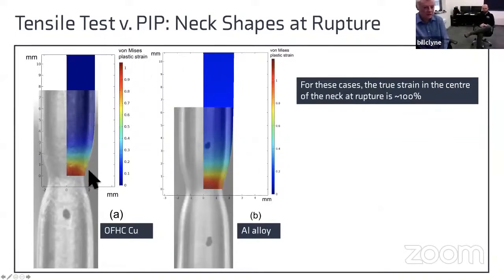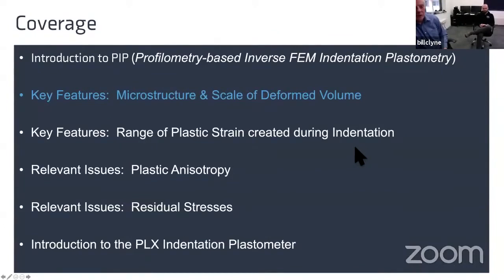These are the von Mises strains as a function of position here, obviously reaching a high value at the neck itself. This is just before rupture, and the level of true strain reached in the neck commonly reaches something like 100% or something like that. What else? Well, there's a number of important features of the process if you're going to get this right. And one of them is the scale.